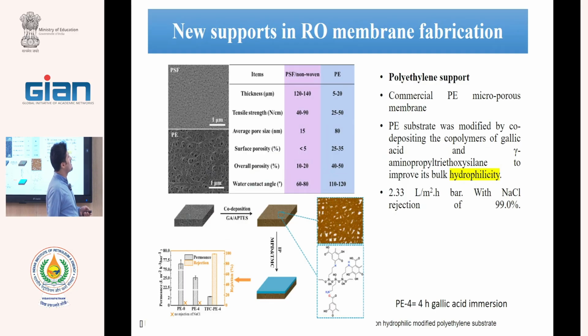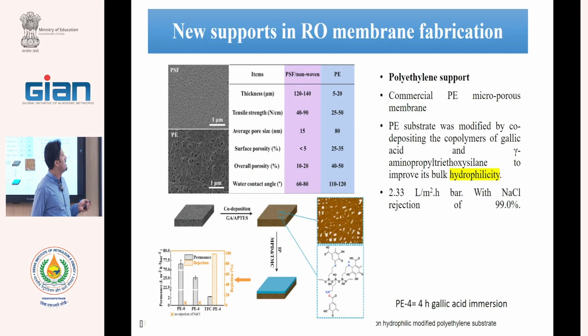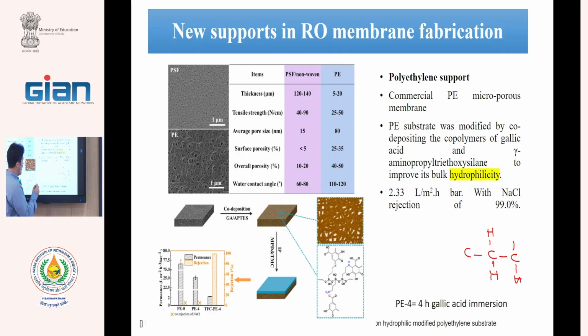reduced. But I say that the supports should have good hydrophilicity, and polyethylene is not hydrophilic. Polyethylene structure is only carbon and hydrogen, okay? But in polysulfone, we have sulfone groups, and these oxygen groups are hydrophilic. Therefore, we cannot use the polyethylene support for fabrication of RO membranes.